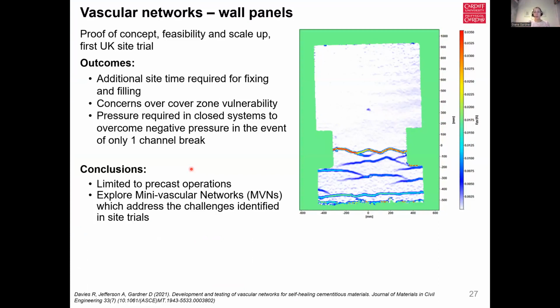Nevertheless, we had proof of concept, feasibility and scale up and the first UK site trial. We realised that we needed additional time for fixing and filling. There were some concerns about the cover zone vulnerability, especially with these channels quite close to the surface. And we realised that we needed pressure in closed systems to overcome the negative pressure in the event of only one channel breaking rather than multiple channels. What were our conclusions? Well, this was probably best limited to precast operations and led us to really think about alternative forms of networks that we could use to address some of these challenges.